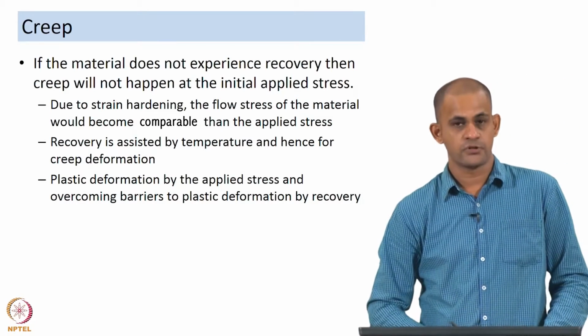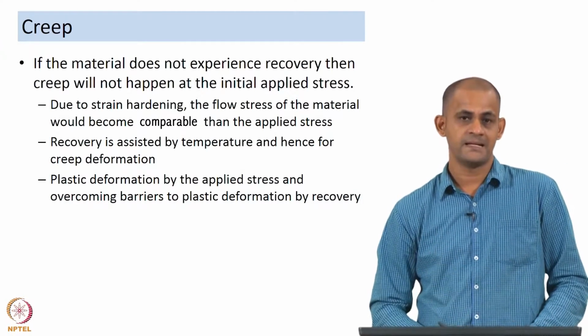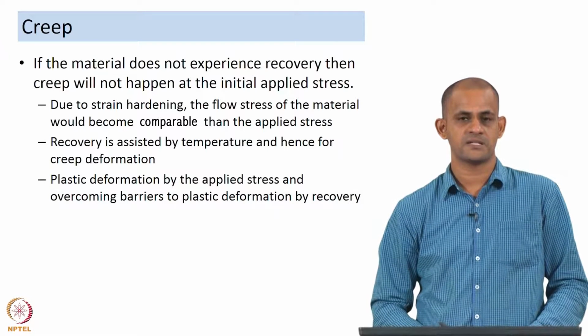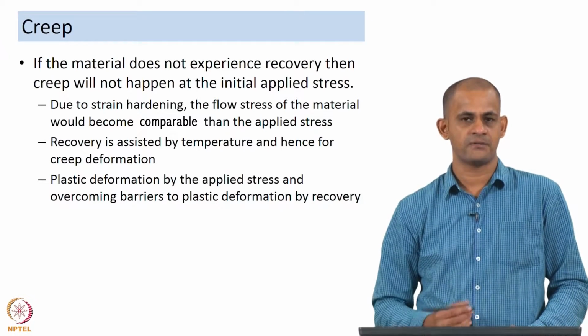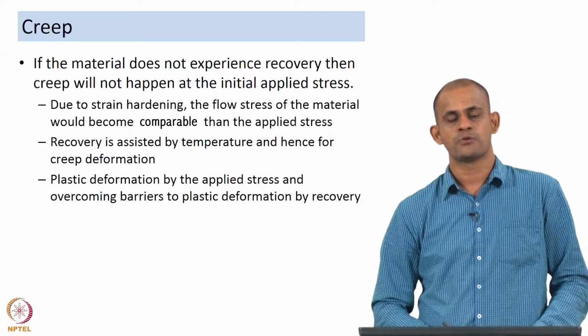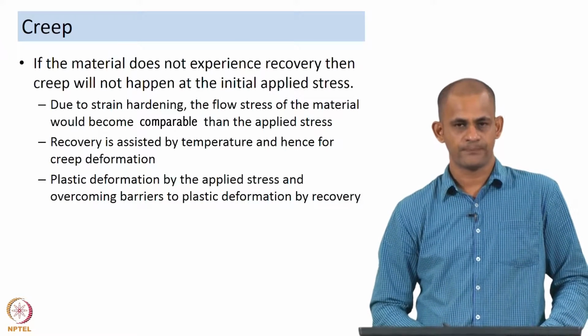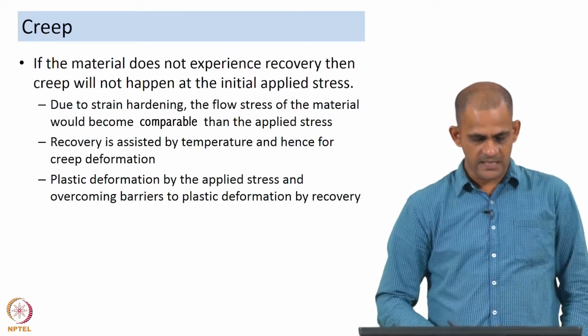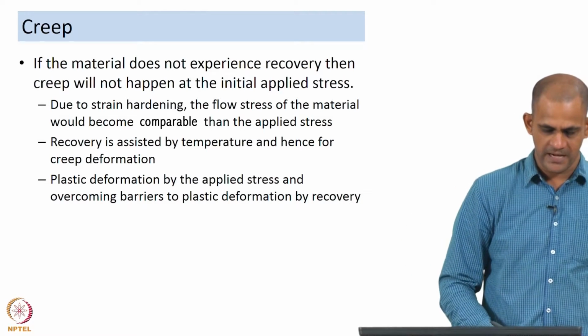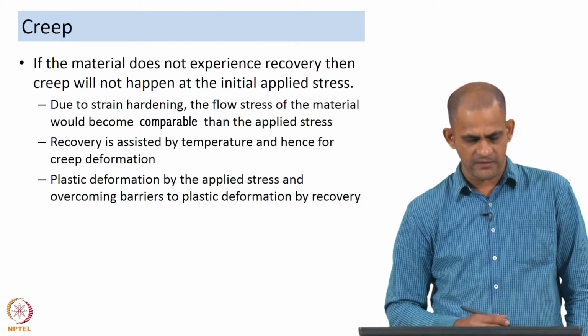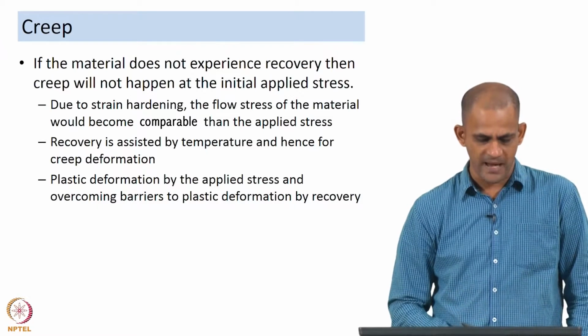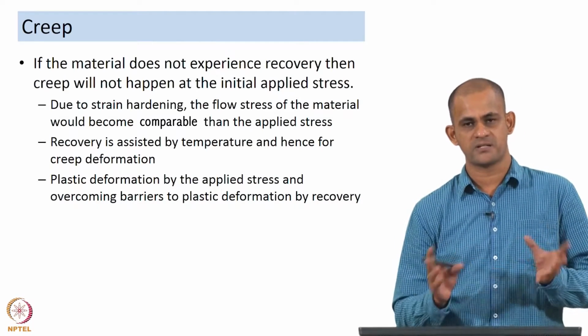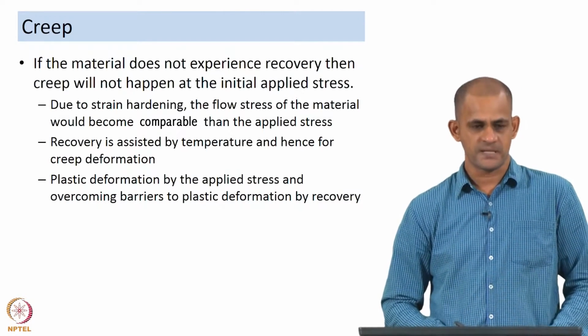material would stop creeping unless there is recovery, which is assisted by temperature, and recovery allows these dislocations to overcome the barriers to motion. So, recovery is important for creep deformation: plastic deformation by the applied stress and overcoming barriers to plastic deformation by recovery, this is more or less what creep is.